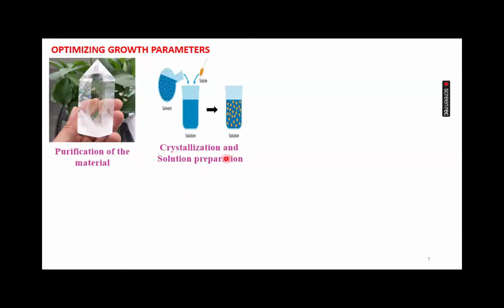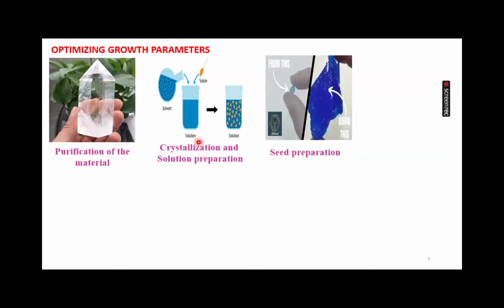Crystallization and solution preparation. The material solubility information at various temperatures is crucial for solution formulation. The solution filtering employs sintered glass filters with various pore diameters. Seed preparation. The quality of the seed crystal utilized has a significant impact on the quality of the developed crystal. In the labile area of the supersaturated fluid, spontaneous nucleation can produce small seed crystals.